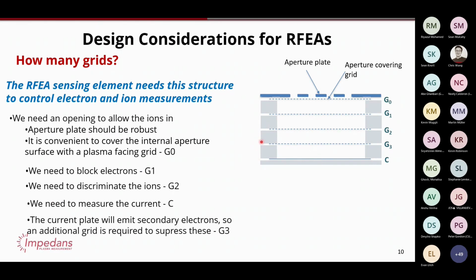And then one other consideration, which is more modern: when ions come in and collide with this collector plate, they have enough energy that the energy deposited is more than the work function of the material here. That means secondary electrons are emitted from the collector. And that would mean ions going in one direction and electrons going in the other direction would add in terms of a current measurement, which would give you incorrect readings.